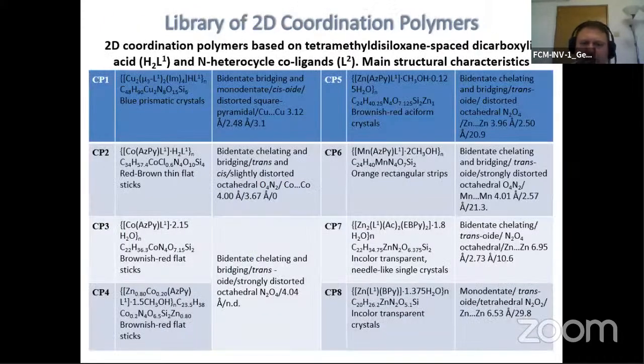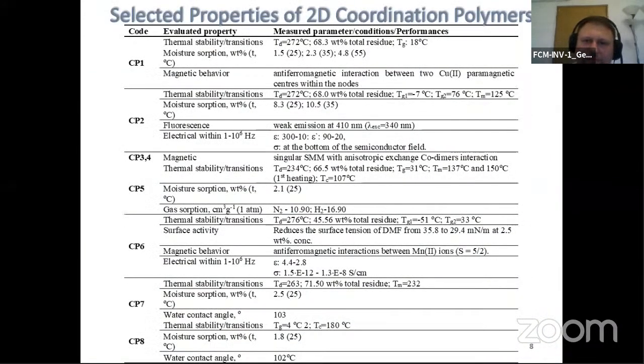So this way, an entire library of two-dimensional coordination polymers were synthesized as single crystals using the tetramethyl disiloxane spacer dicarboxylic acid and nitrogen heterocycle co-ligands, basically by diversifying the permethylated component with synthesis of new carboxylic compounds which contain it, and by its location in the co-ligand. These materials, all these coordination polymers, were characterized in terms of their thermal properties, their magnetic behavior, their water vapor sorption and gas sorption properties.